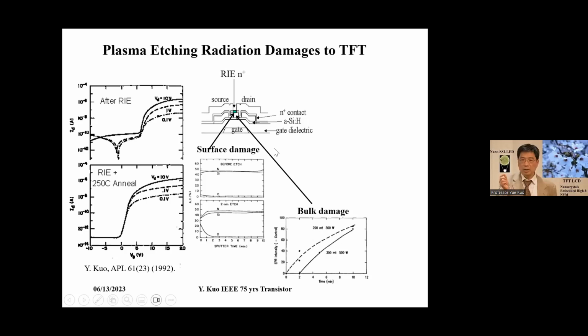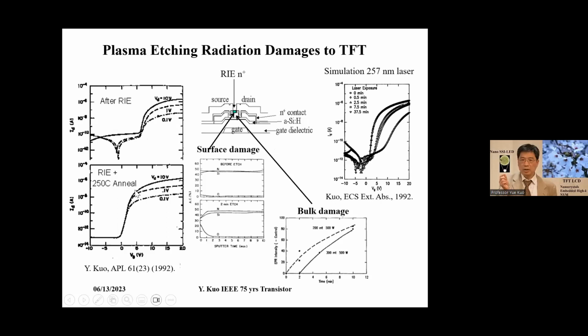ESR shows the damage of the bulk layer. So this interface and bulk layer damage cause the TFTs to behave with a large threshold voltage and high off current. Fortunately, this damage can be repaired by a simple annealing step. So plasma radiation damage is unique, and is not observed in the IC.